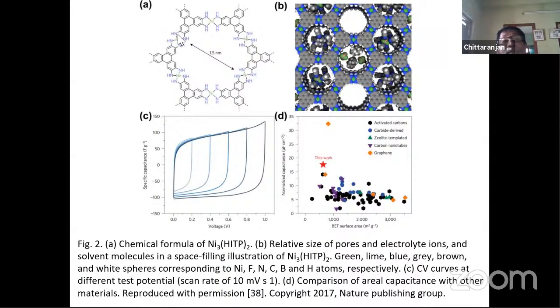Okay, let me come to this one molecule. See, in this molecule, aromatic amines, these amine molecules, are being coordinated with nickel, and this macrocycle is generated, which is also a metal organic framework. This metal organic framework has a cavity dimension of around 1.5 nanometer.